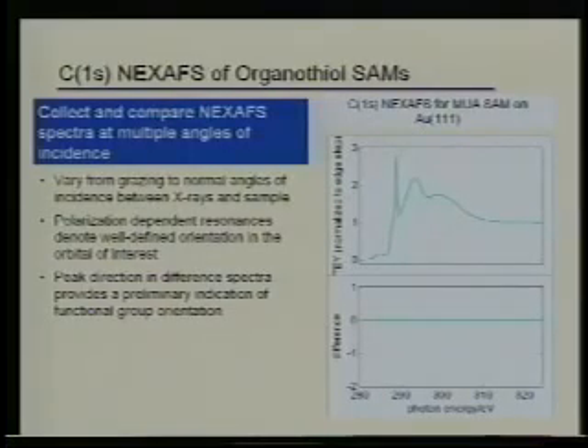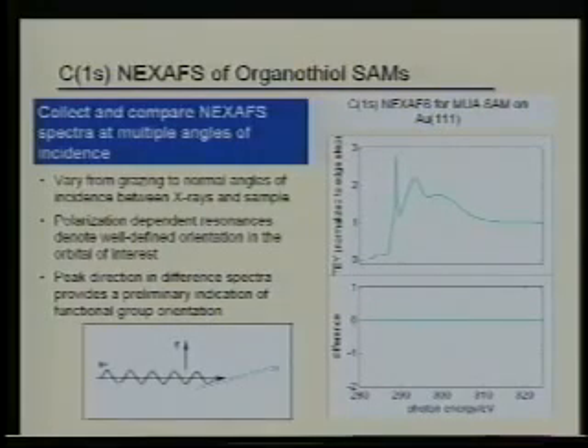So I'm going to show you some of the information you can get by using the polarization-dependent aspect of the near-edge structure. What I've shown here is an X-ray coming into a self-assembled monolayer. Actually, the diagram of the self-assembled monolayer is on the next page. It's coming in at 20 degrees, and this self-assembled monolayer has a carboxylic acid group sticking on the top. And the sharp peak here is actually the carbon double bond oxygen feature.